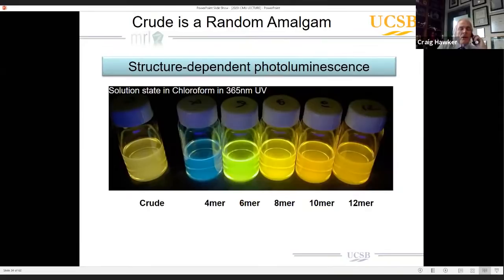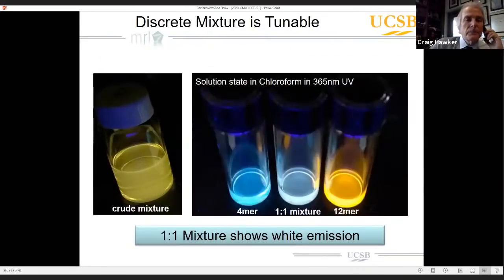But the beauty about looking at oligo-P3HT derivatives is that they are conjugated, and their conjugation length really depends on what the degree of polymerization is. So here you're seeing the crude material that we're starting with has an average DP of about 8, and what we separated into the tetramer, hexamer, octamer, decamer, dodecamer. And just visually, you can see that the photoluminescence of all of these are significantly different, and they're significantly different from the crude starting material.